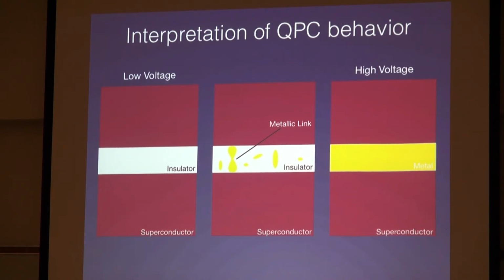I should say that the bias spectroscopy I showed was with a little magnetic field applied, so this wasn't a superconductor, it's just a metal. When you turn up the voltage and you create a metal, and then you just have a metallic behavior in this regime, what I didn't show, I won't show today, is that we've actually studied the superconducting spectroscopy of this superconductor-metal-superconductor system, and it's interesting in its own right. But there's a sort of in-between percolation regime that arises because of disorder in this sample.